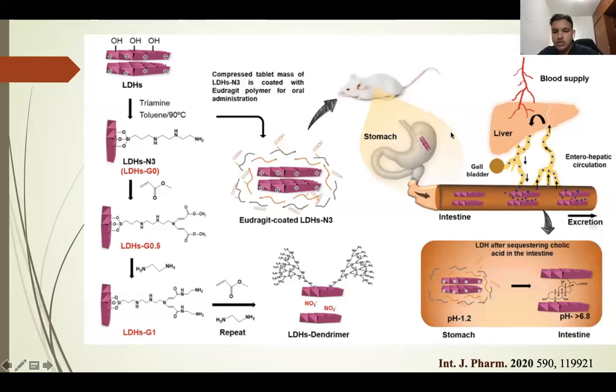The reason behind coating is this could stay safe inside the stomach, where, as I said just now, these layers were sensitive to acid. So the Eudragit layer protects it in the acid, and then when it enters the intestine, it becomes naked. After becoming naked, the cholic acid from the liver could be absorbed inside and then excreted, as it could reduce the cholesterol levels in the body. So here we have observed the different functionalization and dendrimer to see the effect of hydrophobicity on the journey of this LDH.